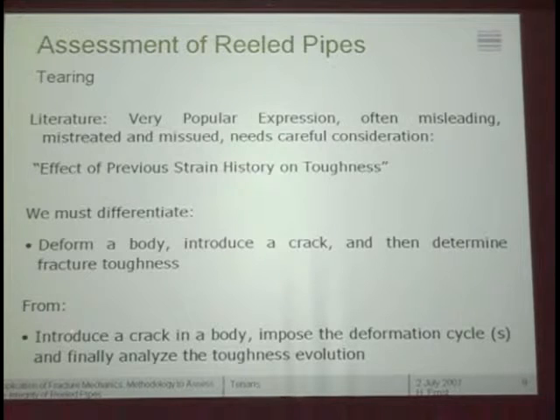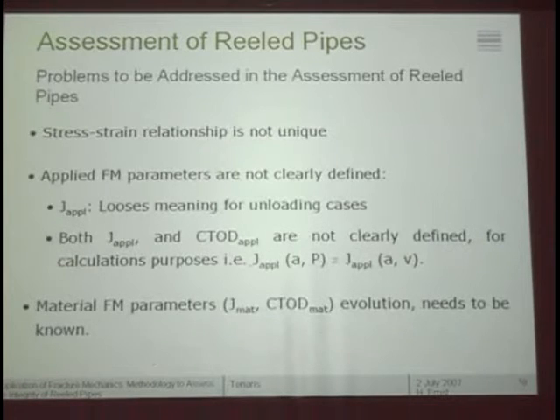That is, if you have a crack from the beginning, impose a certain deformation, and then another cycle of deformation, and see how the toughness evolves with the previous deformation. So it's not the same, and that means that many of the literature results that you can find are not really applicable to this problem.